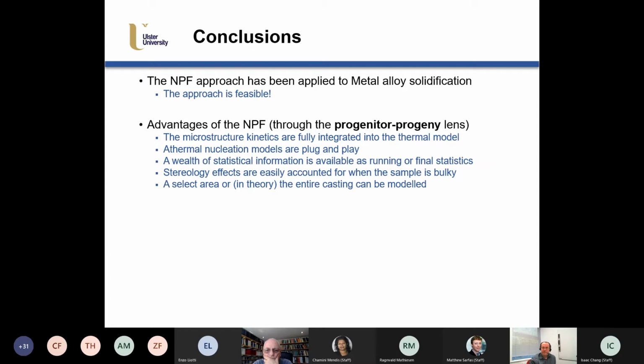So what we demonstrate here is that you can get this progeny function at a particular point. You can look at a select area within the field of view, or you could, in theory, model the entire casting using this approach. So this method can be scaled up to any casting to give global information. Temperature gradients: a nice benefit of looking at the convolution principles and pooling all this information together is that low temperature gradients don't really present a problem. As long as the growth is equiaxed, it's low gradient, then we're able to model that using this approach and combining all those statistics I've just mentioned in the presentation.